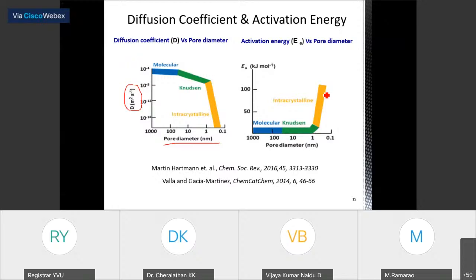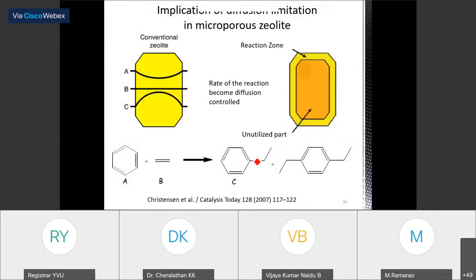In the case of microporous material like zeolite, intracrystalline diffusion requires higher activation energy because of the difficulty experienced by the molecules to diffuse into the micropores. So it reflects in the efficient use of the catalyst.